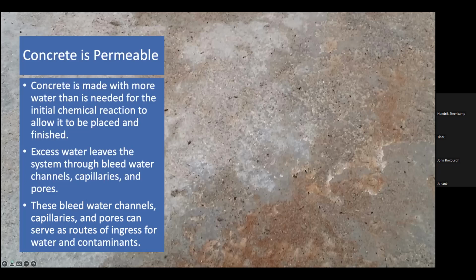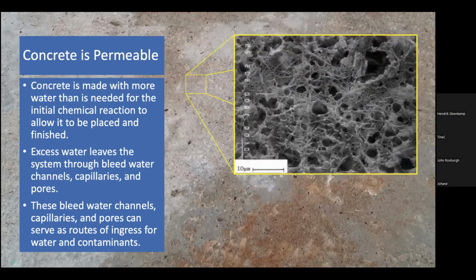And the reason is that this was evidence to me that some reinforcing steel corrosion was occurring. Now, reinforcing steel corrosion is the major reason that concrete doesn't last as long as we want it to. If we can figure out a way to slow or stop the reinforcing steel corrosion, in many cases, we can greatly extend the life of concrete. So this is an exaggeration of what the permeability of concrete looks like. It's not this wall's concrete, but I wanted to show you that under a scanning electron microscope, you can see that concrete is permeable.